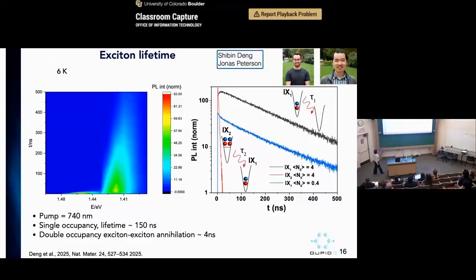And then we can also look at the dynamics of this exciton. At the low density limit, the single exciton, these are interlayer excitons, so they have pretty long lifetime. I mean, compared to atoms, they're still very short. But compared to other excitons, in the single exciton limit, if we just look at this lower energy peak, the lifetime is about 150 nanoseconds.